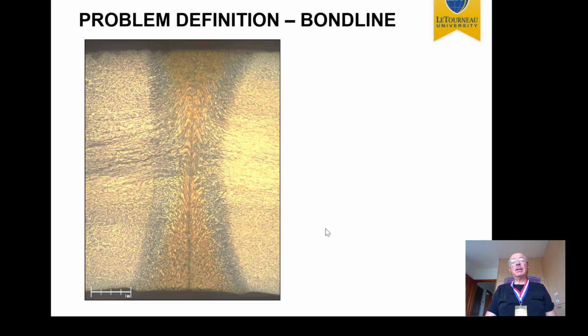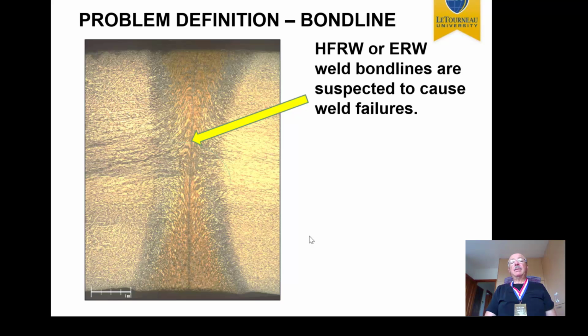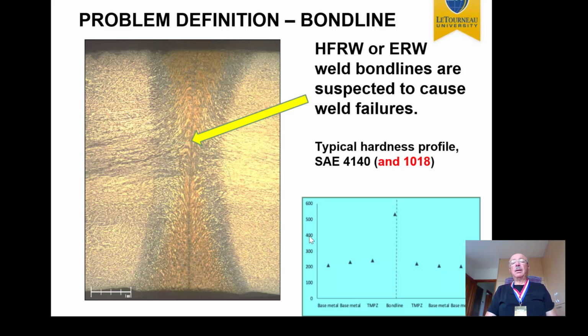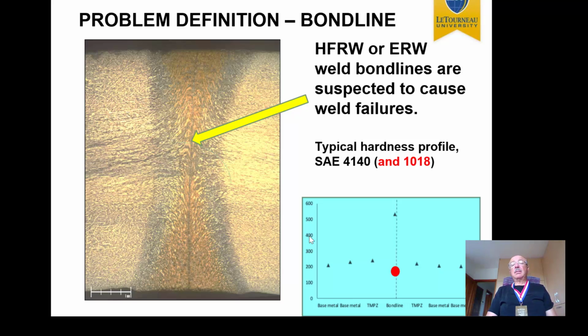So what is the bond line? The topic of this talk is this particular little line in the middle, which is highlighted by this arrow, which has different characteristics than the rest of the weld. Many times people suspect that the bond line is a source of failure, and that's why I wanted to have this conversation to give you some idea, because when people sometimes measure the hardness in that region, they find it excessively high, like in this case. Yet sometimes if you weld a different grade, like a 1018, it is much lower.